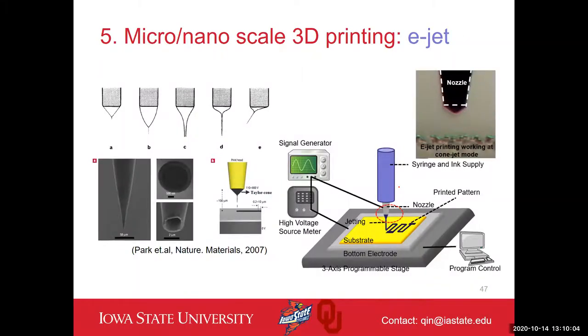So I will briefly introduce the fundamental theories and then get into certain applications where we can collaborate. As I mentioned, the fundamental idea for e-jet printing is to apply a high voltage and use electrical force to drive the ink flow out from the nozzle. While we apply the high voltage, it will drag the ink and form a cone shape over here. This cone shape is called a Taylor cone. And if the electrical force is big enough, it will overcome the surface tension of the ink. So only a small drip is going to form at the tip of the nozzle.